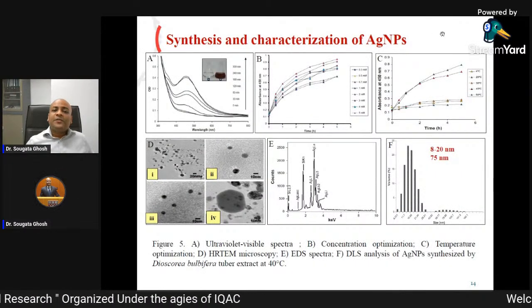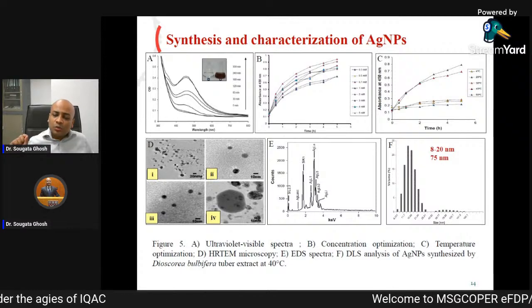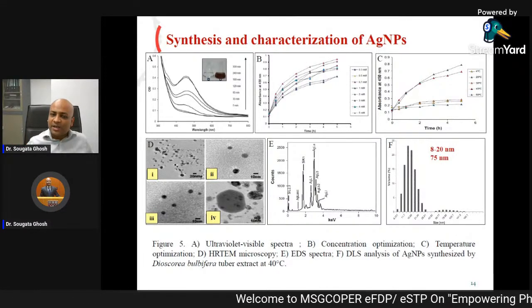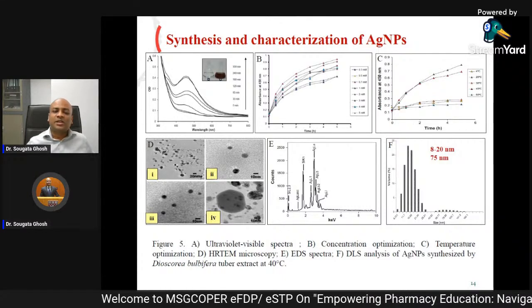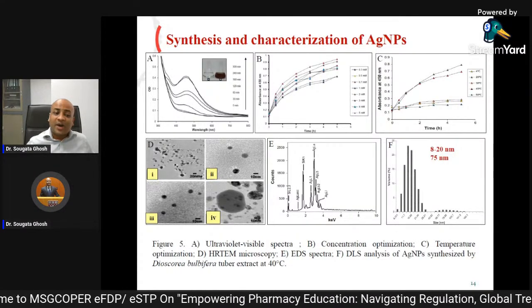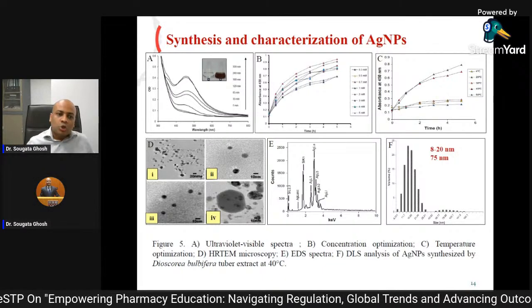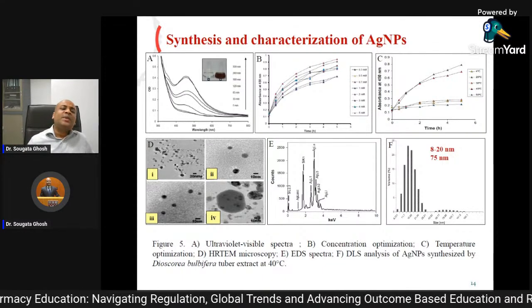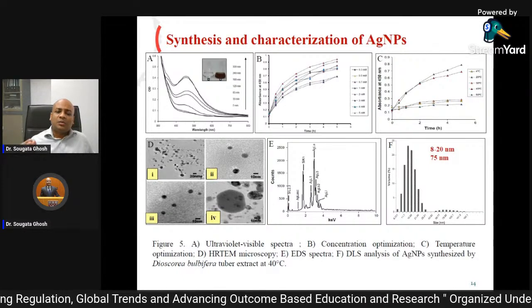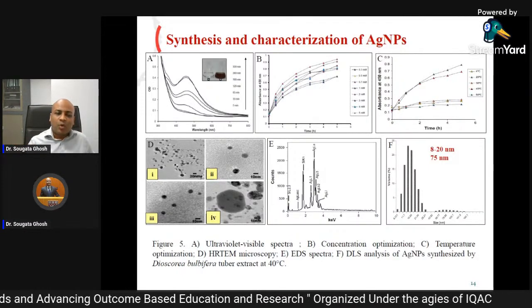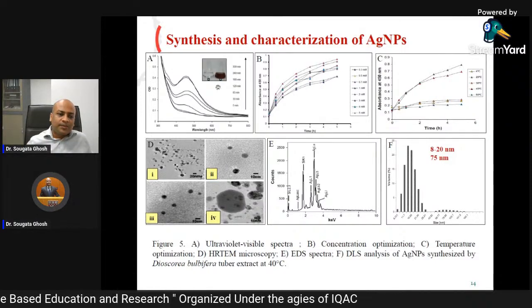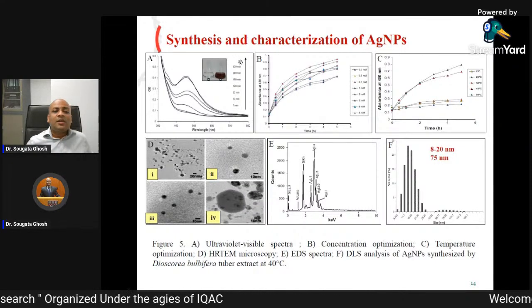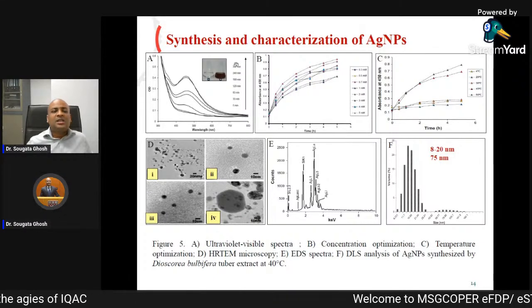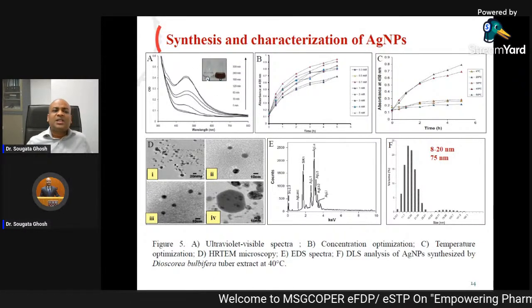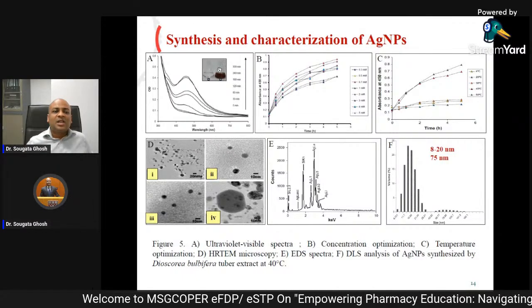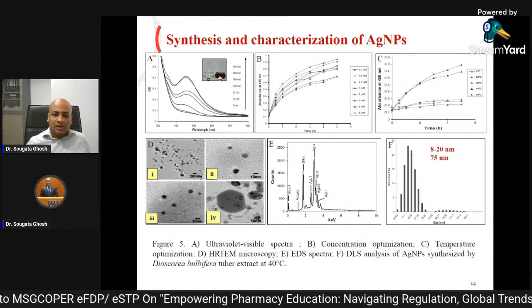Next, we thought, if this Dioscorea bulbifera can prepare the gold nanoparticle, can it prepare silver nanoparticle? In Ayurvedic literature, it is written that Dioscorea bulbifera or Varahikand can prepare Rajat Bhasma also. The Bhasmas are very, very small, biologically transformed forms of metals. So we thought, can it produce these silver nanoparticles? And within 5 hours, 300 minutes, the silver nanoparticle was produced. You can see this is the silver nitrate solution, and this is the silver nanoparticle that is brown in color.